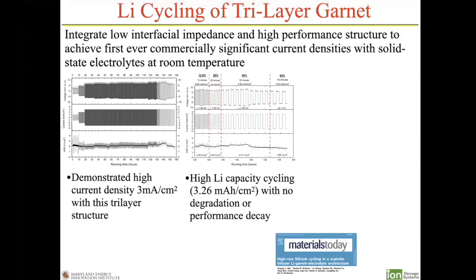And what we did is, at 3 milliamps per square centimeter, we went to more and more time on each cycle, corresponding to more and more capacity of lithium cycling. We're going up to 3.26 milliamp hours per square centimeter, which is 10 to 15 microns of lithium that's cycled with no degradation or performance decay.